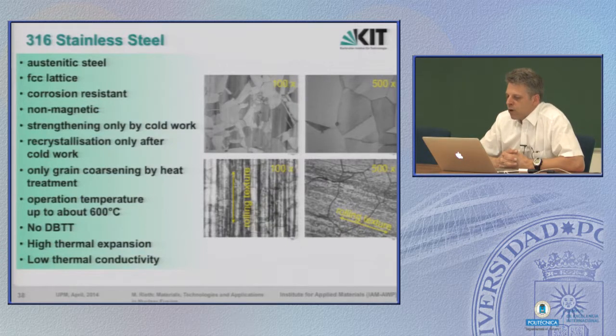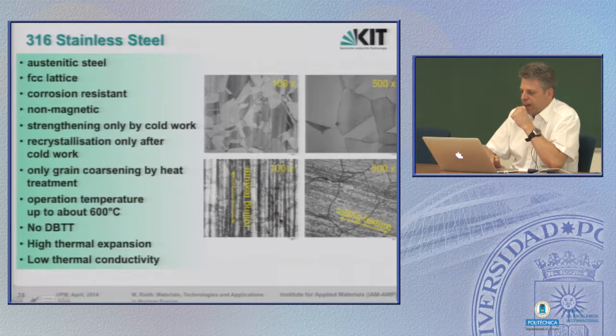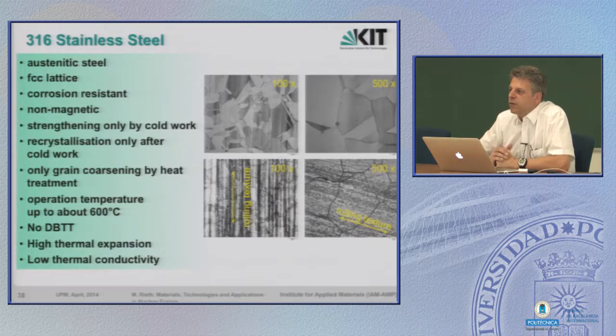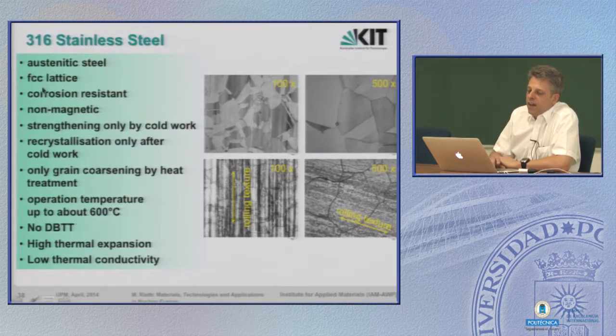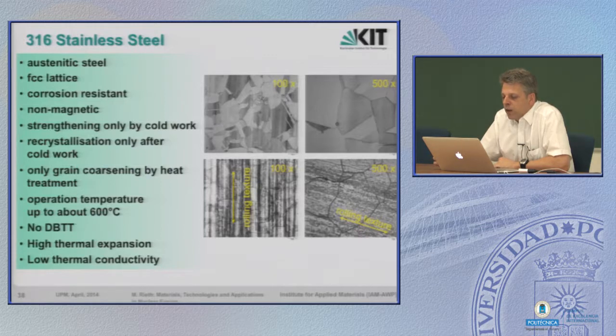This is a summary of the behavior of the 316 steel and how it looks. Most often, you see the remainder of the rolling or forging direction. If it has been produced in huge quantities, you always have to take this into account, that you will never get a perfectly shaped and perfectly structured steel. But anyway, it's an austenitic steel, has an FCC lattice, is corrosion resistant, and one very beneficial property for fusion application: it's non-magnetic. In fusion applications for the confinement, we have to deal with very strong magnetic fields, and so it helps if your structural material is non-magnetic.